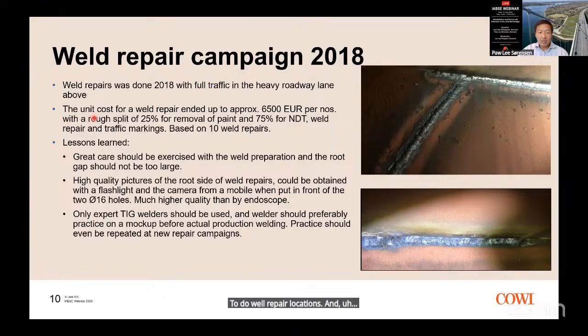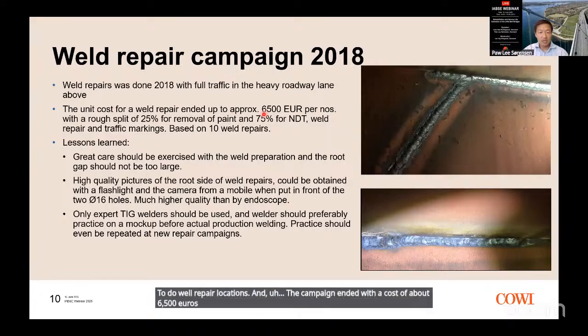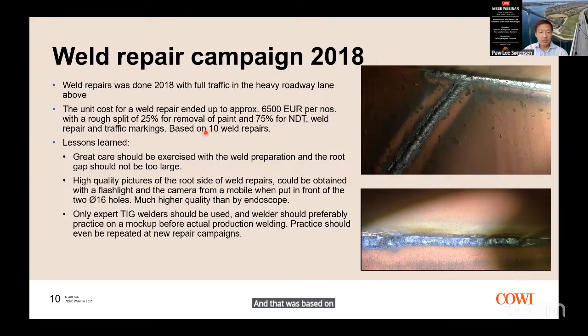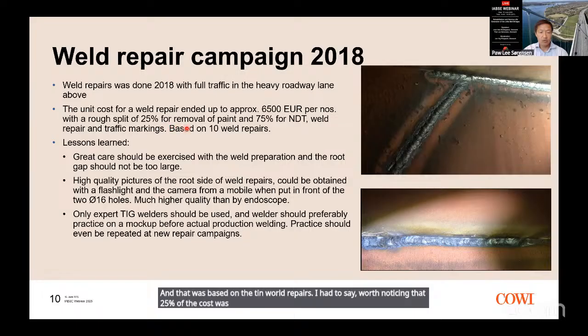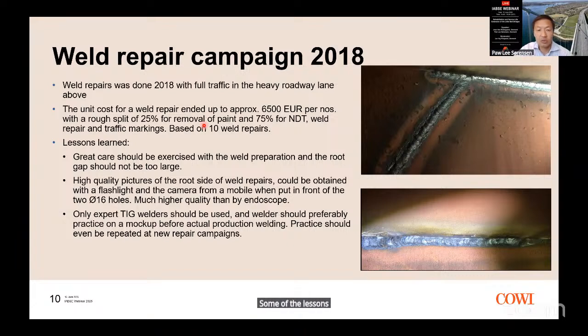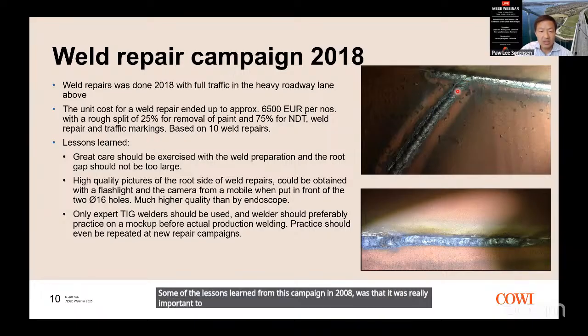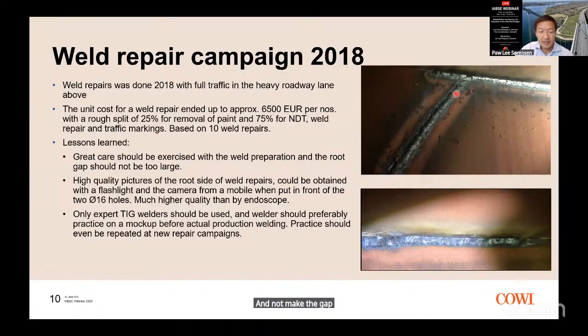The campaign ended with a cost of about 6,500 euros per repair, and that was based on 10 weld repairs. Here it's worth noticing that 25% of the cost was due to removal of the paint. Some of the lessons learned from this campaign in 2018 was that it was really important to exercise great care when removing the weld and not make the gap too big.